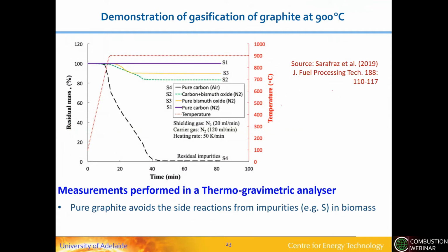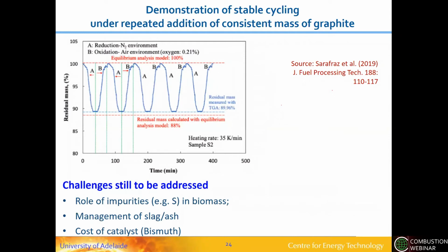So one of the examples of some of the work that we have performed is demonstrating gasification of graphite in a molten metal. So this shows that much as a gasification reaction can occur under other conditions in other reacting environments, the temperature is relatively modest at about 900 degrees, which is lower than some of the reactor environments because of the high reactivity of the metal. Obviously graphite was chosen to avoid some of the challenges of things like biomass and waste, which can also have other complex components, but we were interested in the principle here. We think there are probably a number of limitations to this process because of the availability of carbon sources, so we're more focused on some of the other media, but showing that the reaction can cycle through this molten metal media stably.